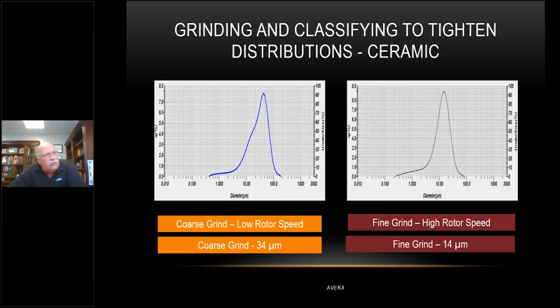So we're going to want to classify this again. When we went to a higher rotor speed, I think this is at about 200 RPMs, and this is at about 800 RPMs. And the difference is we go from a 34 micron to a 14 micron cut, a little tighter distribution than we saw on the lower speed, but still too many fines on the end of this thing. So what we're going to do is let's first look at the SEM.